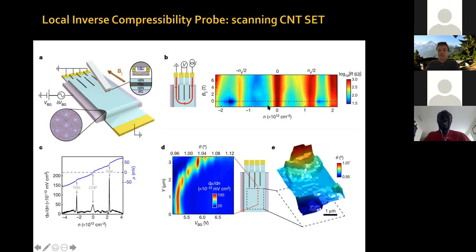So it turned out to be a Magic Angle Graphene device, but it was a little bit disordered. This doesn't matter too much for Shahal because he can scan and locally check the response in a particular region. For him, it's actually okay if the twist angle varies substantially because he can just pick whatever region he wants. Anyway, it's not a high quality device from the global transport point of view, but it's good enough that you can measure correlated insulator states at 2 electrons and 2 holes per Moiré unit cell and superconducting domes, for electrons and for holes. This is the transport in log scale versus parallel magnetic field.